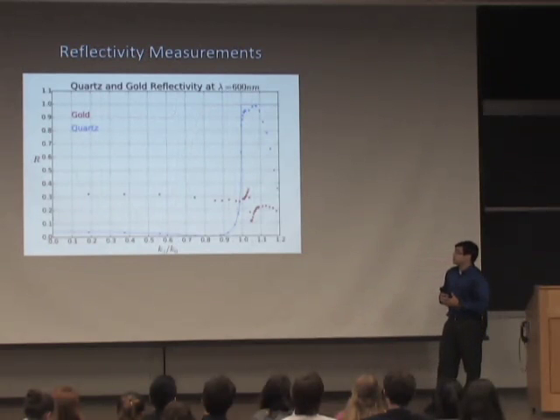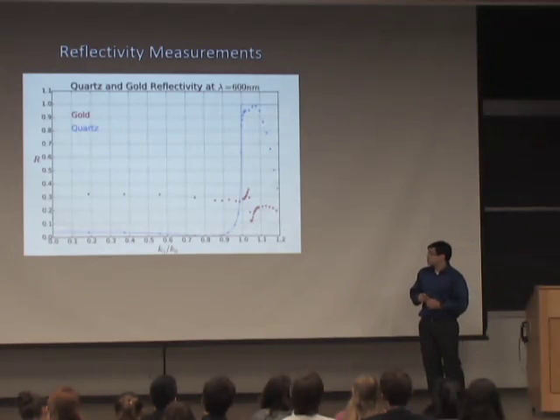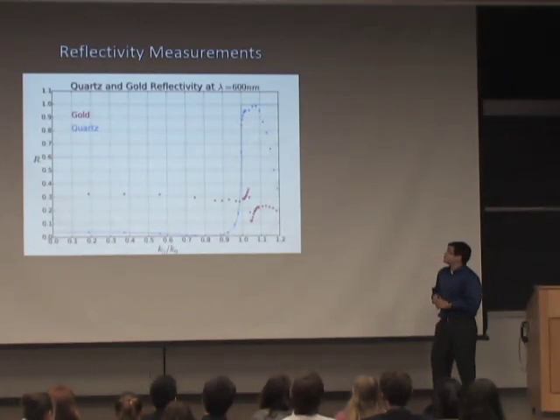So looking at our actual data, we can see the quartz cover slip by itself, no gold on top. The blue line starts off with very little reflection as it just goes straight through the quartz. But once you reach the critical angle, it's all reflected. You get near 100% reflectivity.